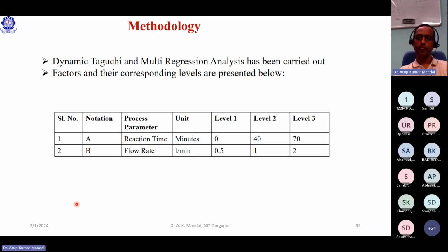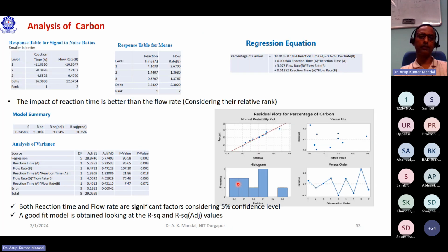Here, we have taken three flow rates, 0.5 liter, 1 liter, 2 liter, and time 0, 40, and 70 minutes as level 1, level 2, level 3. And from the regression analysis, if you see, both the reaction time and flow rate are significant factors at the 5% confidence level. You can see both are significant parameters. So here the good fit model was observed considering the R square and adjusted R square values. This is for the carbon.